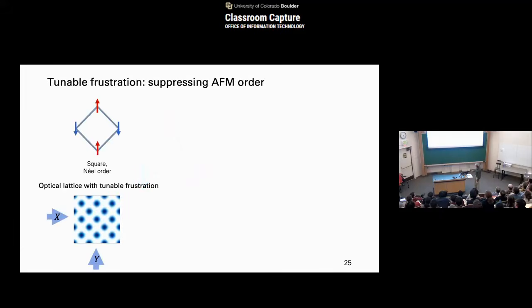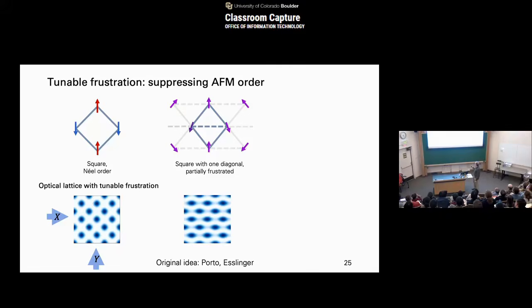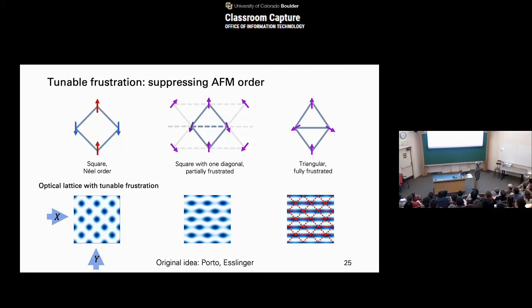So how can we create triangular lattices? There are different ways to do it. You could directly have 3 lattice beams interfere, for example, but we do it a bit differently. We have interfering lattices here in the x and y direction. If the two don't interfere, you get a separable lattice. If they do interfere, you get a non-separable lattice with the potential landscape as shown here. And what we can then do is lower the lattice depth in one direction, and that way we can continuously tune from square to triangular geometry, just by turning on this diagonal tunneling across one of the directions.